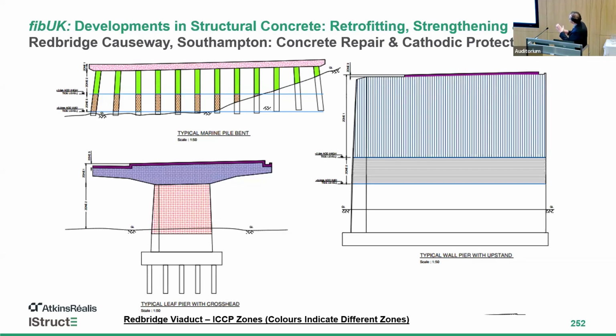Regarding the zonings, these are the typical zoning that we use for the pile bents, as Kevin mentioned, the piers and the leaf piers. Part of the structure was obviously tidal, so the current demand in the tidal zone, because of the salt and the moisture in concrete, was higher. Hence, those zones have to be maintained separately and controlled differently compared to the atmospheric part of the structure. And also the bearing shelf, which was just below the joint and exposed to leakage. Again, the current demand was different. And the anode system for the bearing shelf was different, for example, from the rest of the leaf pier. Hence, the zoning was very critical for that structure.